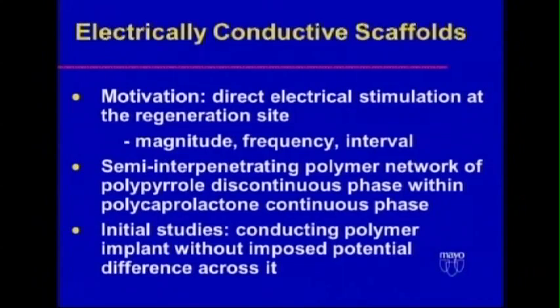Usually when things work, somebody has a great idea like Brett did. It seems really simple. We make the nerve tube the way we always made it. He dips it in the initiator for a while. It diffuses in and covers the pores. Then he dips it in a monomer. When the monomer diffuses in, it meets the initiator in the pores, and it makes a semi-interpenetrating polymer network, meaning the polycaprolactone part is the continuous phase, and the polypyrrole is a discontinuous phase within the pores.